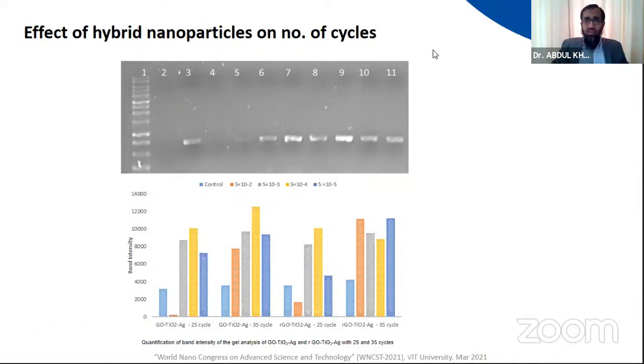Okay, so what you see here is the effect of hybrids. We have established that PCR efficiency could be improved using graphene, carbon-based materials, hexagonal boron nitride, and metal oxides. Different metal oxides have been used: copper, silver, alumina, and so on and so forth. We also established this using hybrid materials. So if, for example, you have a 2D structure, you can decorate it with 3D structures, and with different combinations of 3D structures, such as what you see on the screen, graphene oxide, TiO2, and Ag silver can form a fantastic hybrid material with higher conductivity. But the only challenge in this case is stability. These particles are highly dense, and as a result, they tend to settle down. Nevertheless, you can still see enhancement taking place. This also proves that many materials which are chemically not going to react with the PCR reagents can be formed as hybrids, and you can use them as potential PCR enhancers.